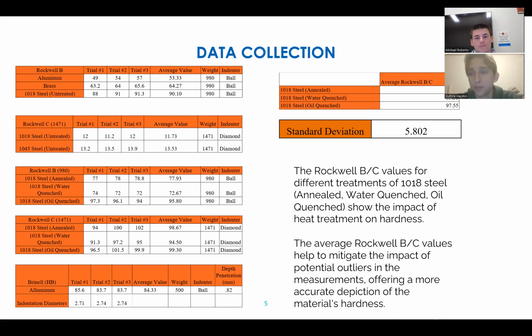Awesome. So in our data collection, we had 3 different trials, and that averaged into the final value that we used among the aluminum, the brass, the 1018, and the 1045 steel, both when it was annealed and treated with oil and then water. This is important because the surface of the material that we're testing is not completely homogeneous. It's not completely flat, because of previous labs or maybe just small microscopic issues. So we took 3 different tests to have an exact value, so that we could measure our expected values for the Rockwell test, just in terms of accuracy.